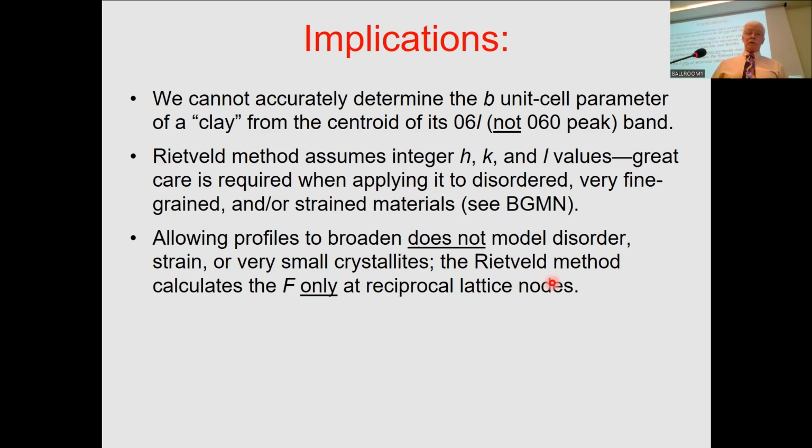The other thing is, remember, the Rietveld method uses hkl, integer values. Be very careful. There are a couple of approaches that have been devised in the last 10 years. BGMN is one of them, by some of the members of the audience, and they more correctly treat these issues. But don't use an off-the-shelf Rietveld program and plug in delta functions for broad asymmetric peaks.